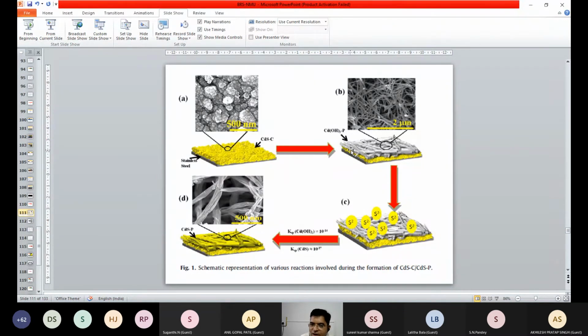Very interesting, right? Just by dipping cadmium hydroxide inside the sulfur solution, sulfur from the solution comes inside, and the hydroxide part goes outside, called an ion exchange process, right? So whatever hydroxide is replaced by sulfide ions by ion exchange. But the most important thing is that during this exchange process, the morphology of the cadmium hydroxide, which is in the nanowire form, is not changed; it remains intact, it remains the same, right? And it means that cadmium hydroxide is used as a template for the formation of cadmium sulfide nanowires. Do you understand? Cadmium hydroxide nanowires are used as a template for the formation of the cadmium sulfide nanowire.